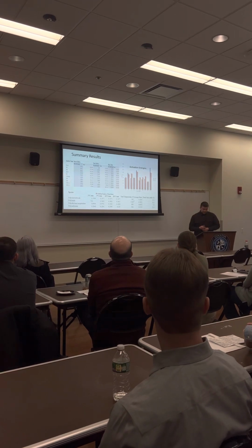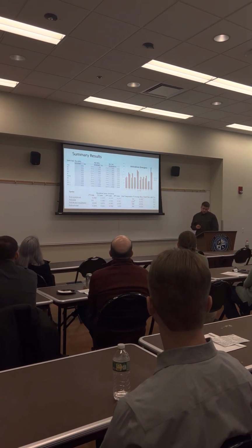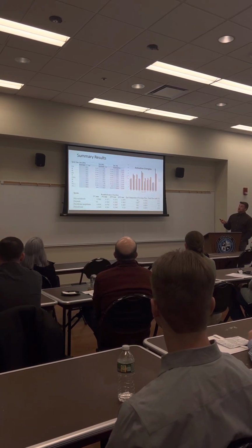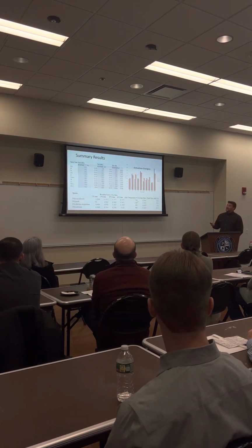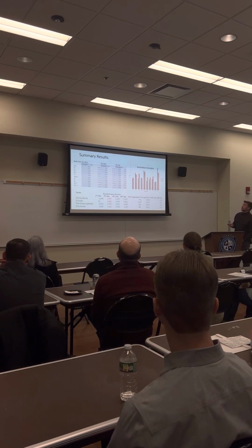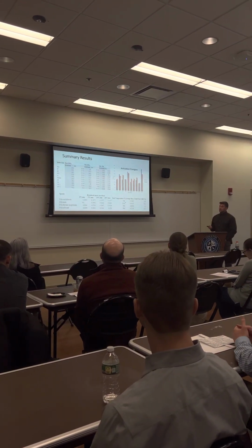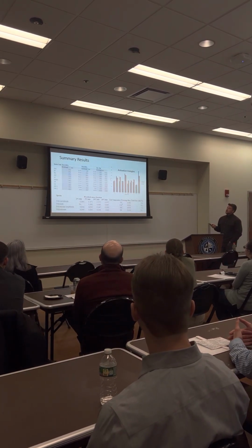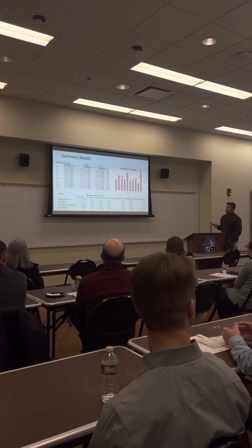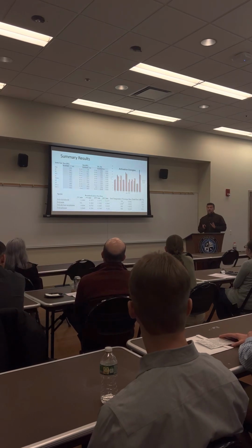So this table summarizes the results of what we got in those plots. Here we have the Kissinger peak, the peak REL, and the peak onset. REL stands for the Rich E. Lyon approach. He's sitting right here. We used the math to compare these kinetic values, and you can see the peak method using the REL approach and Kissinger method are almost the same. They only vary slightly in that temperature is squared in one of the denominators in the previous equation. And then the kinetic parameters obtained using the onset temperature have a different value. This gives insight that there's a difference in the first half of the reaction than there is in the middle of the reaction, or the 50%.